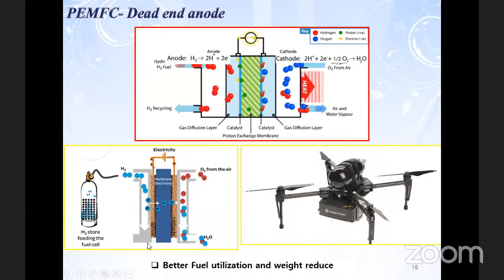Okay, so what we do here in aviation, we get a very limited hydrogen from this tank, and instead of recycling it, we block it. The other end is blocked. So whatever hydrogen is there, it's being utilized. But in this case, the pressure, the hydrogen feeding, is very important because it should not break the catalyst layer, the gas diffusion layer, the proton exchange membrane.